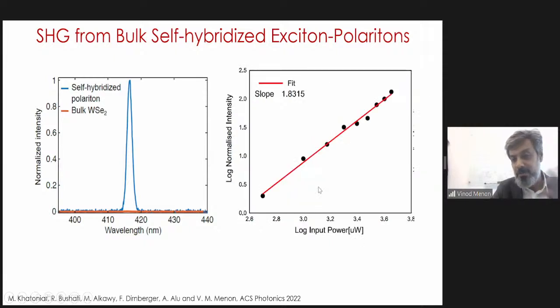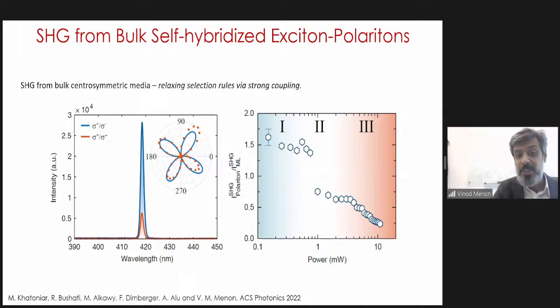So, and of course, you have a quadratic dependence, so we know it's second harmonic that you see. We also saw that it obeys the crystal geometry. So you can rotate the crystal and you can see that it has this flower-like pattern, which indicates that it is not a surface effect. It's actually coming from the bulk of the material. And in fact, in the low pump power limit, you actually see that the second harmonic from this Polariton system is greater than even the monolayer. So are we really relaxing selection rules for nonlinear optics via strong coupling? So that's really the question we wanted to understand, and why is this happening?